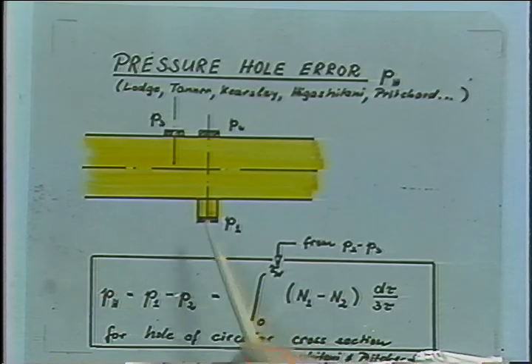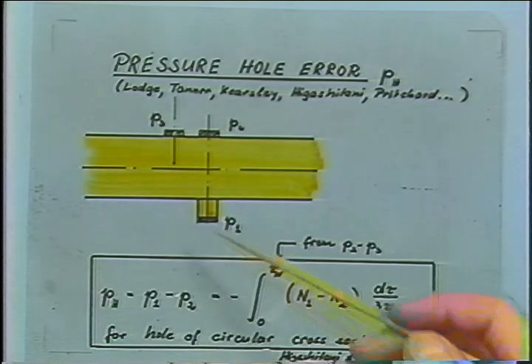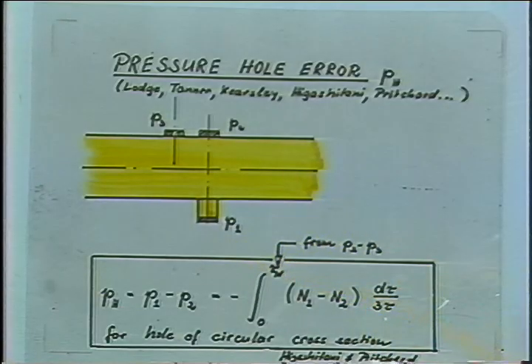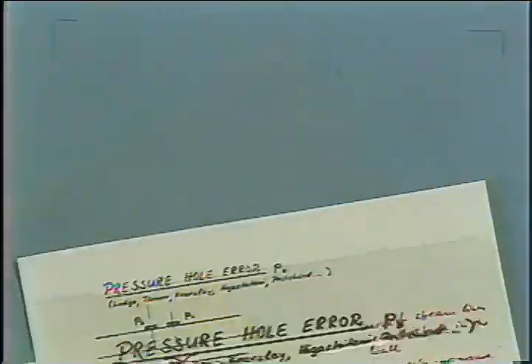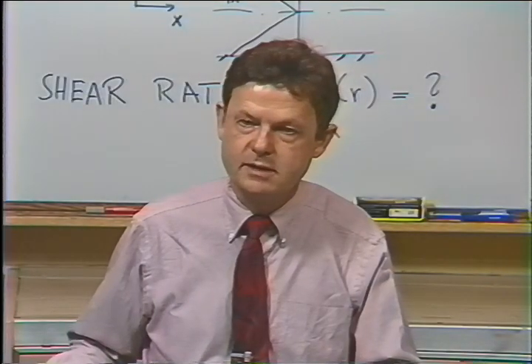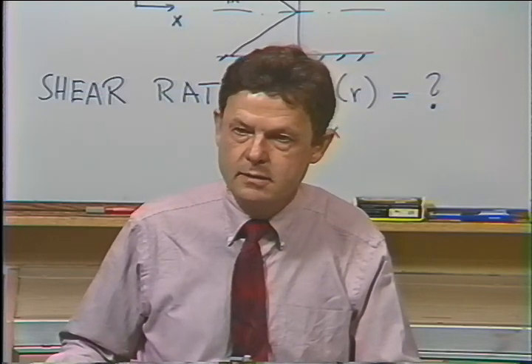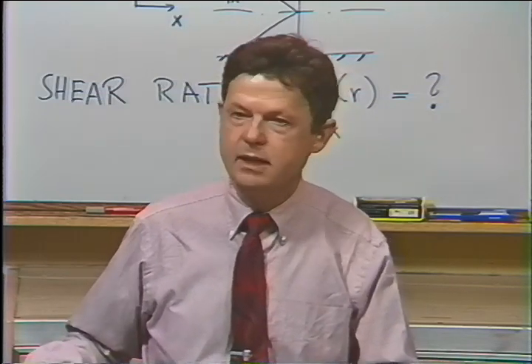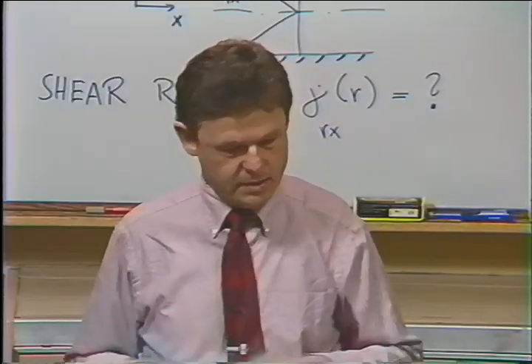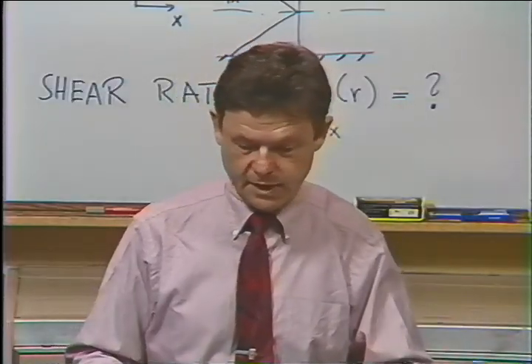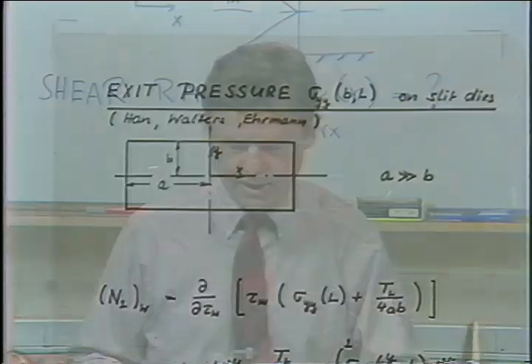Into that system there's a deceleration and acceleration involved. And for Newtonian liquids, the inertia effects are the only effects which give rise to different pressures, and this has been analyzed in detail. But for elastic liquids, in low Reynolds number flow, the inertial effects are very small, and we indeed could obtain very nice normal stress functions with that setup. Arthur Lodge in Madison, Wisconsin, built an apparatus and is promoting that type of experiment to determine N1, and he got nice data. Another proposal goes like this.